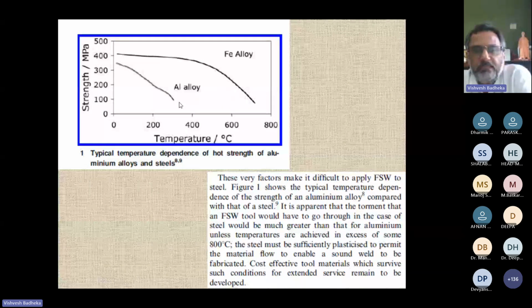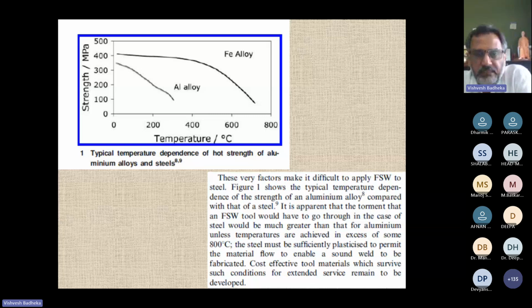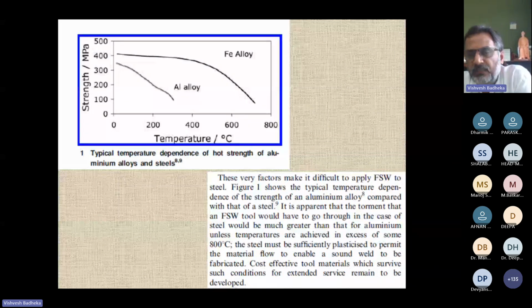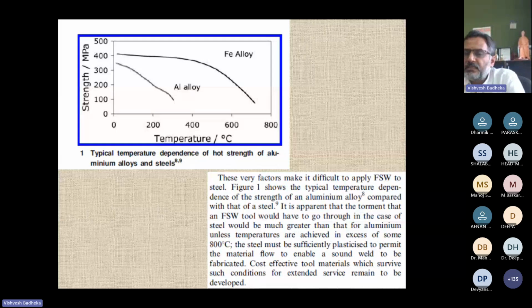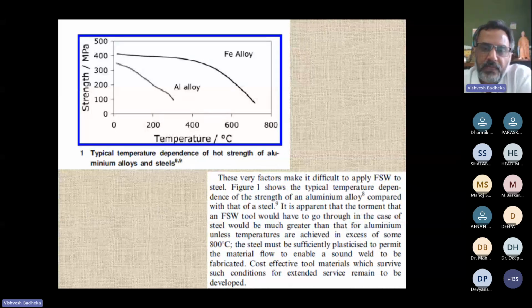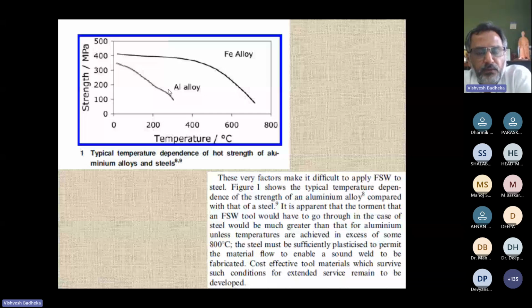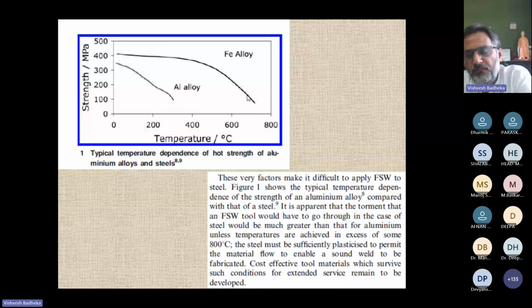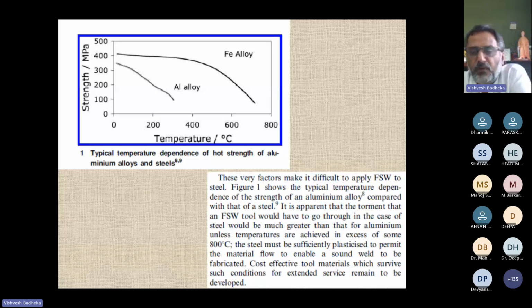You can do it easily in the case of aluminum, magnesium, or a soft material because the temperature is just 200 to 250 degrees centigrade. But getting this 600, 650, 700 degrees centigrade through friction stir welding is a challenge. So that's the reason for the additional heating, which we have discussed just now, either with the laser, the GTAW, the plasma, the oxyfuel, the induction, or the ultrasound. It will help you to increase the temperature, and the load on the tool and wear of the tool will reduce. So that's very, very important, I would say.